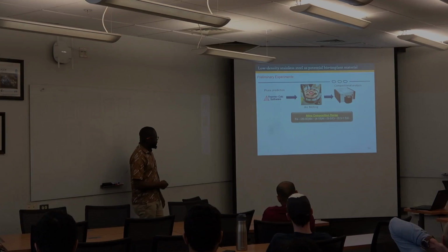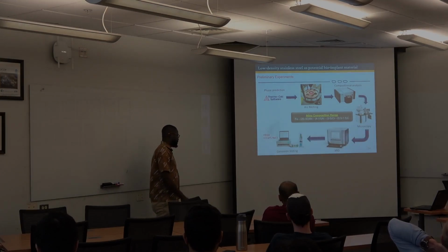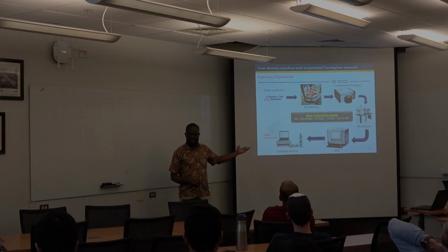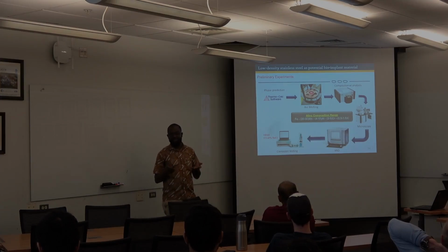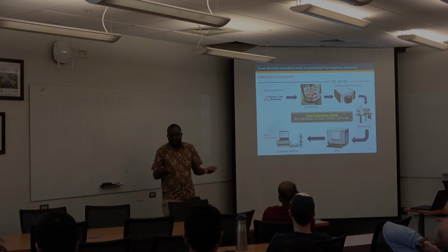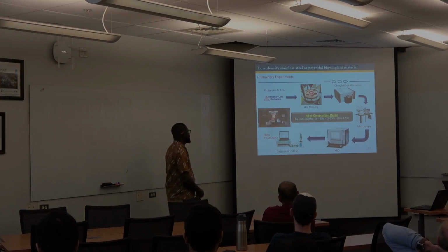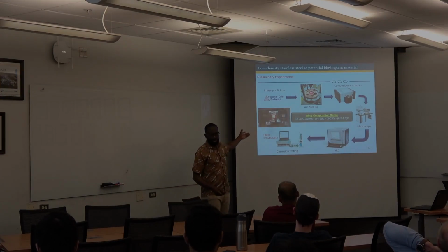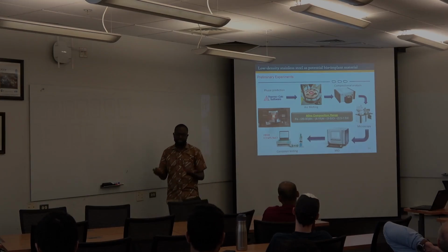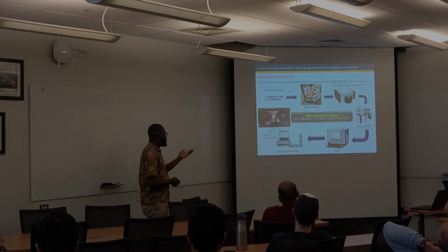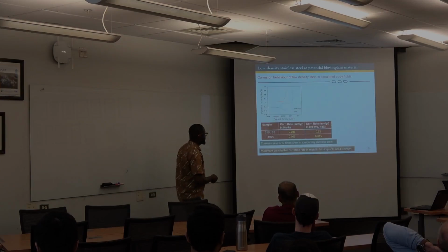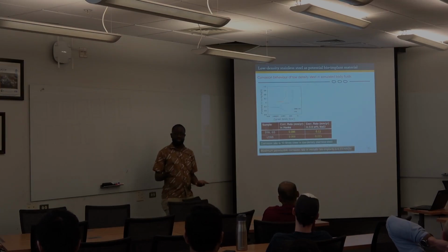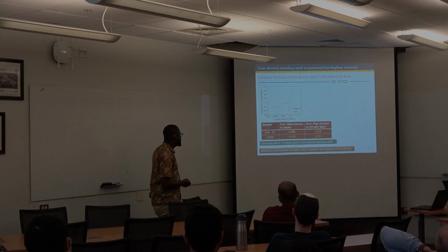And then we produce and we do compositional analysis, microscopy, XRD, and of course, then we do linear polarization, because the first thing you want to establish in preliminary studies is what the corrosion behavior is like. And then I love to include my area, deformation, to see what's going to happen. And I'll show you why this was necessary. And again, I also have more questions than answers eventually. So this is just one of the preliminary experiments.